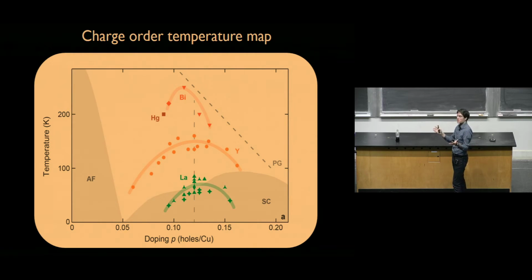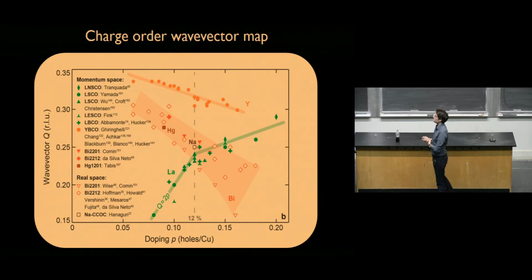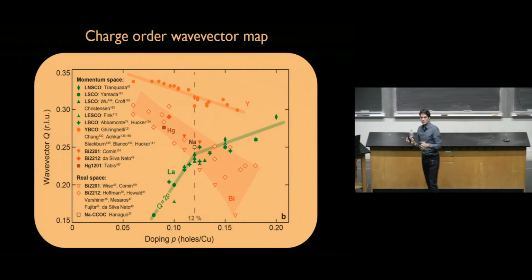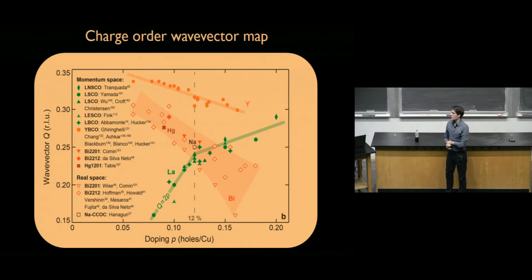This is one of the big discoveries of these last few years. And it appears at different temperatures for different compounds, which is not particularly surprising. That is also the case for superconductivity, for instance. But in all cases, it's maximum around this kind of magical doping of 12%. And the reason for that is not yet very well understood.